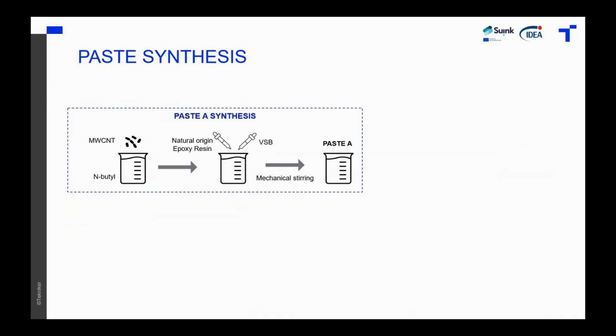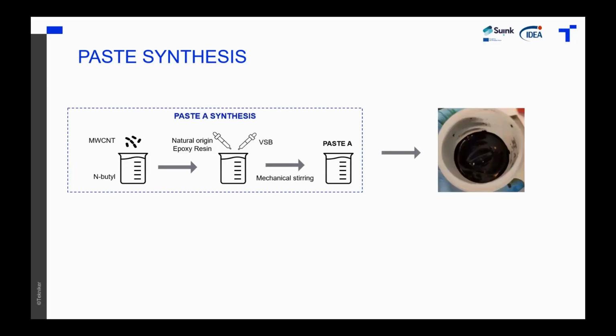what we did was to first disperse the carbon nanotubes, in this case in n-butyl, because this is the solvent that is compatible with the epoxy resin. Then after dispersing it, we added the natural origin epoxy resin and its hardener, and by mechanical stirring, we get the paste that we could see on the image.